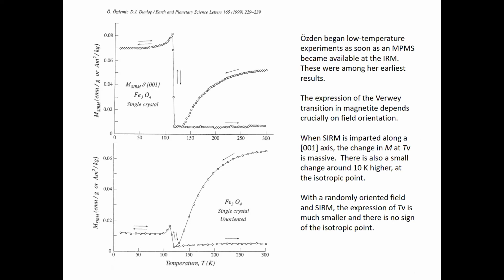This was in the early days, an expression of the Verwey transition in magnetite, which clearly depends a great deal on the orientation of the crystal. If you put an SIRM in at room temperature along an easy 001 axis, you get an enormous expression of the Verwey transition. But if you put it in just in a random direction, the Verwey transition is still there, but not nearly so obvious. Another thing that you get in the high resolution plot at the top, or the large expression of the transition, is a little hint, just in one data point there, of the isotropic point, which is almost never seen in data at about 10 degrees above the Verwey transition.